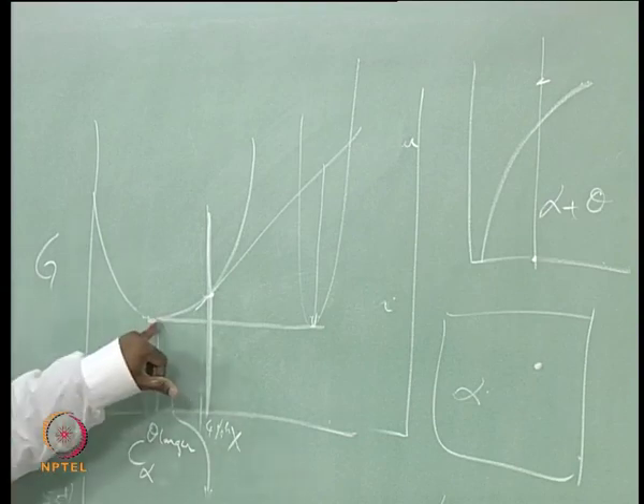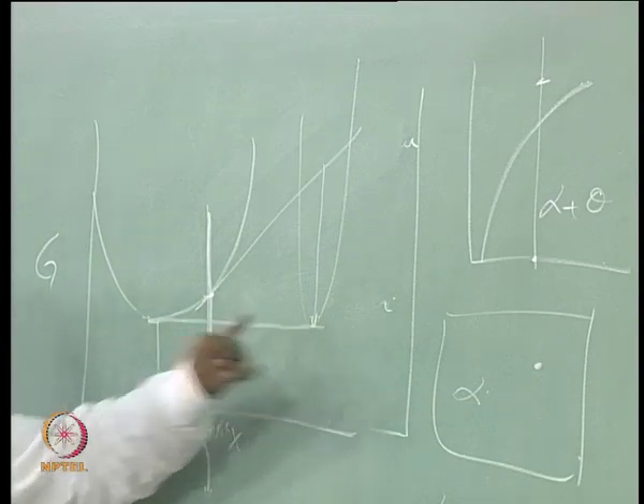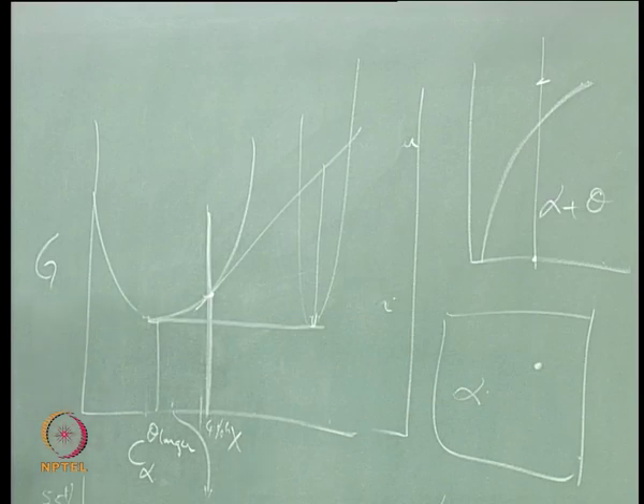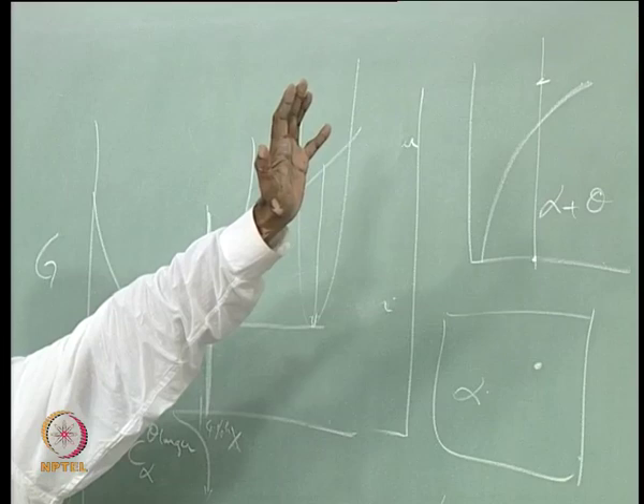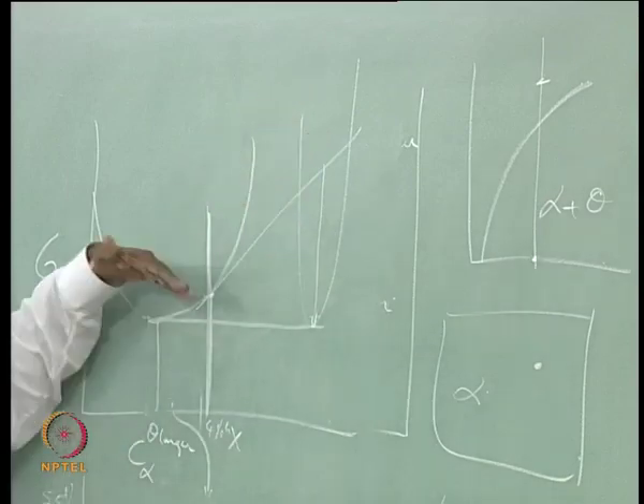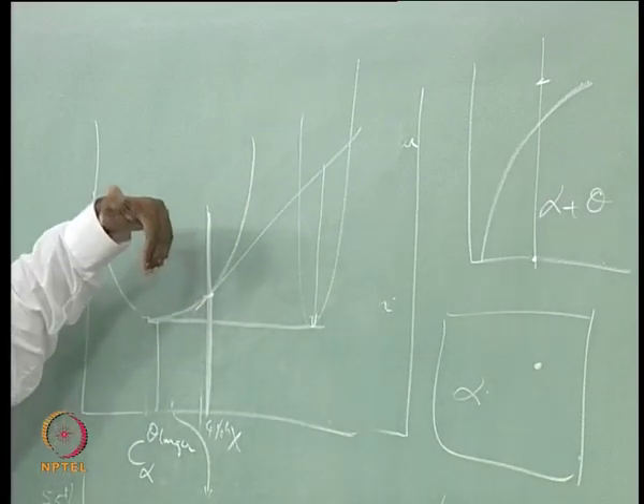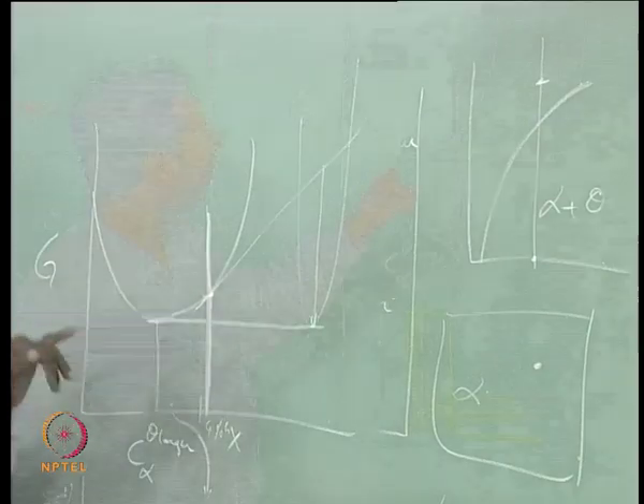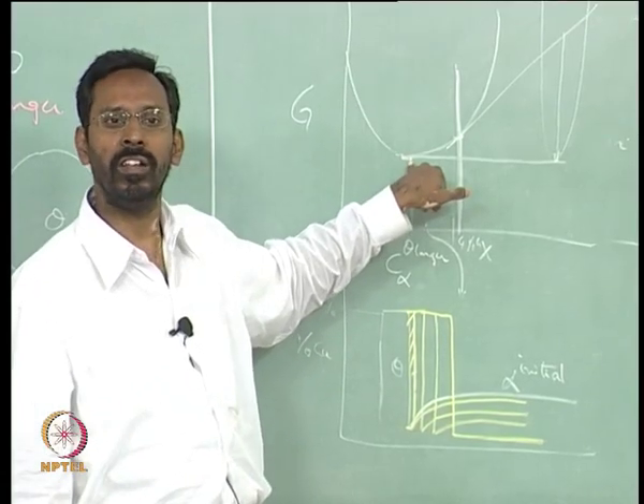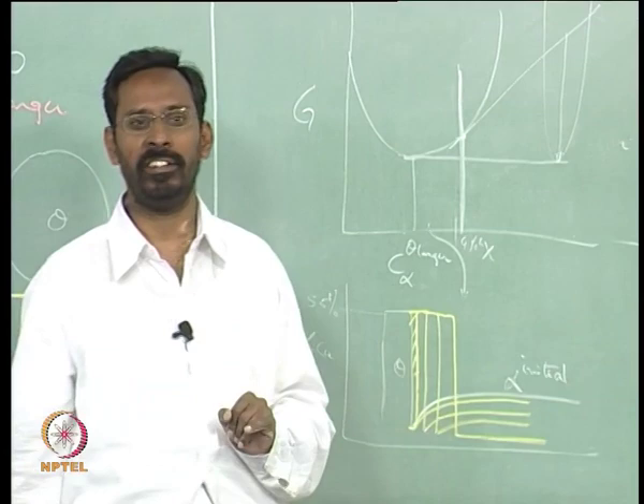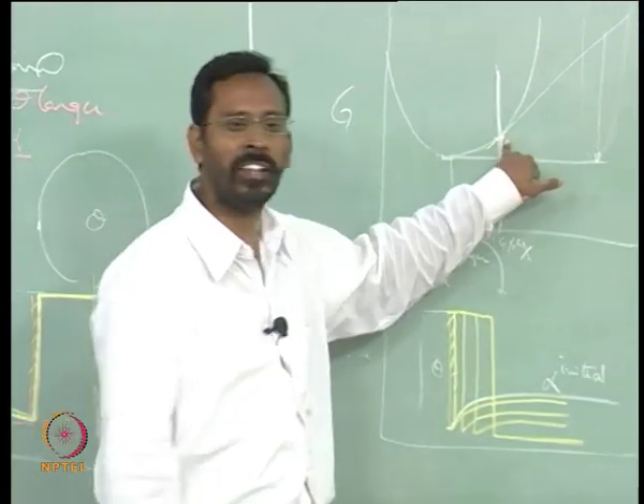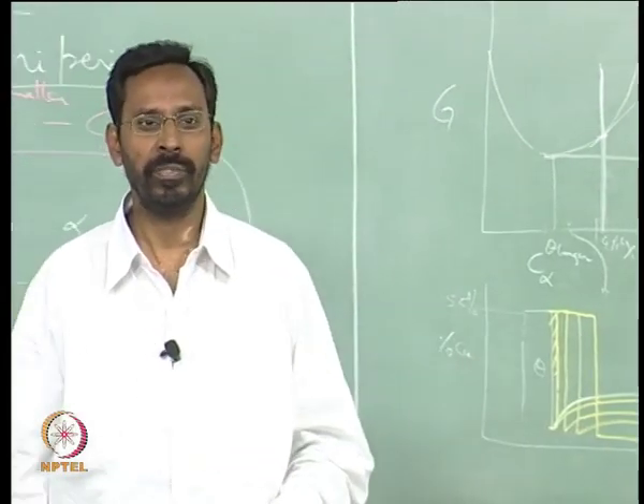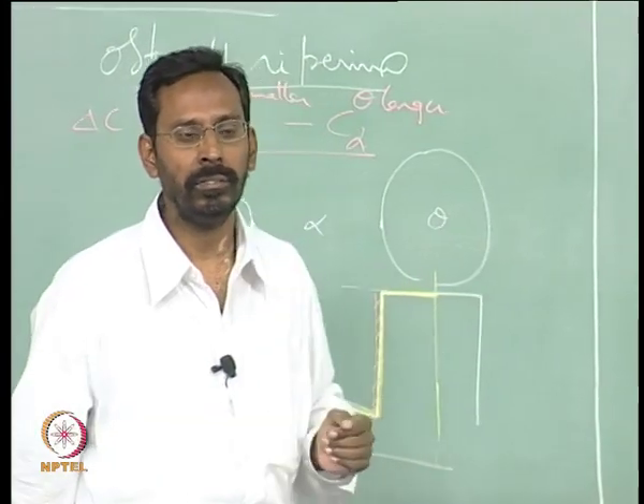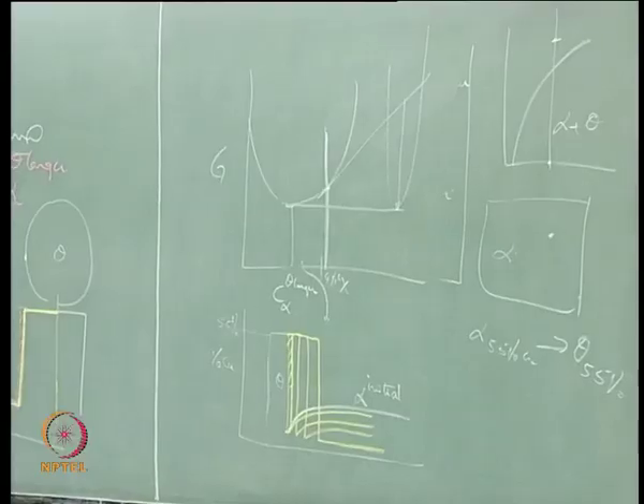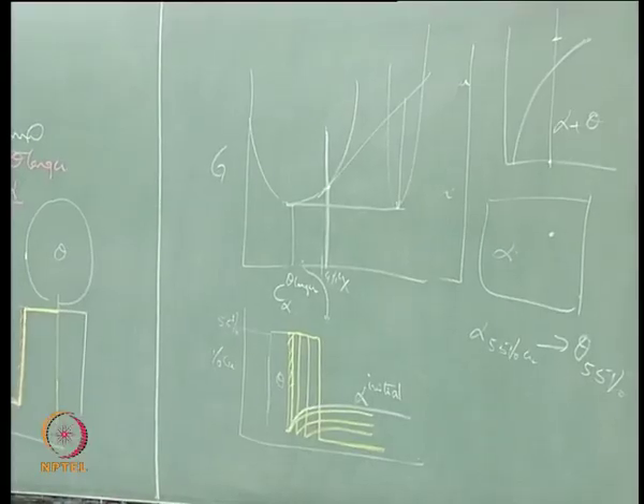So, the alpha which is in equilibrium with theta has a lower composition, and the alpha which is far away from this nucleation site still has the starting composition. The starting composition is this, and the composition in equilibrium is this. This is the gradient we are talking about. If this difference was not there, there would be no gradient. Clear? But the theta immediately after it splits, the grain size is very small.